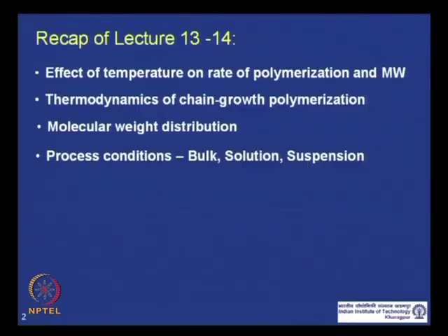So, to recap the last two lectures, we discussed in detail the effect of temperature on the rate of polymerization and molecular weight, and we found that in most cases if you increase the temperature, the polymerization rate goes up and simultaneously the molecular weight comes down, except in the case of photopolymerization. And we discussed the effect of pressure on the rate of polymerization and molecular weight very briefly, and we talked about the thermodynamics of chain growth polymers.